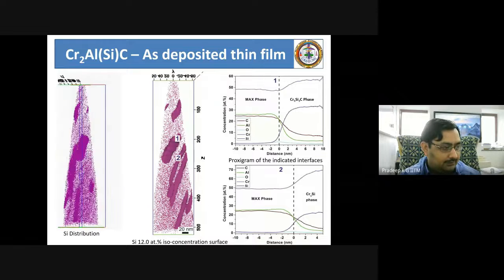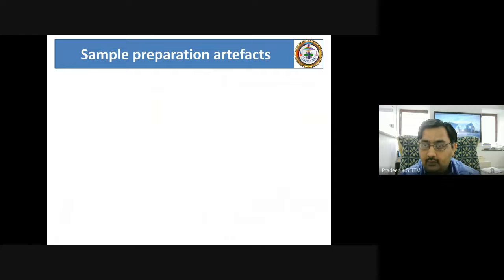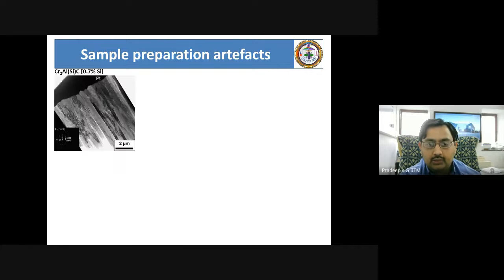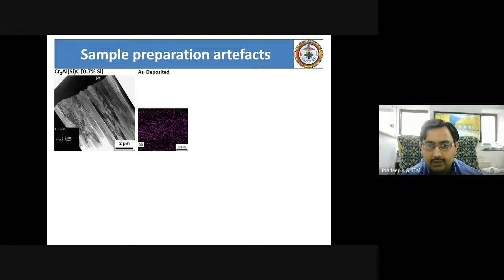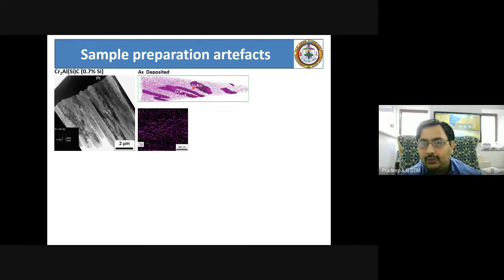So now if you want to understand why we are able to see something in atom probe and why we are not able to see something in other methods, that means the same material with 0.7% silicon, we looked at in TEM, we are able to get a single phase diffraction pattern, whereas if you look at the same in an atom probe, we are able to see multiple types of silicon segregation in the form of a precipitate. If you try to understand this, from the EDS pattern, you can see this silicon distribution in high resolution, whereas atom probe tells you there are two different types of precipitate, which is much more pronounced segregation compared to what you see in a TEM EDS pattern.